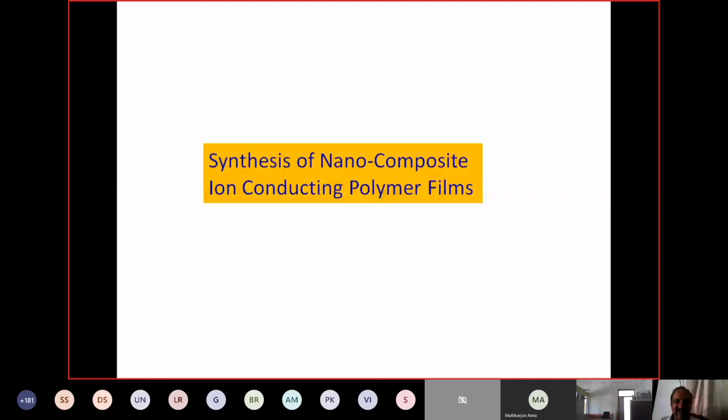So because of that only we are adding these nanomaterials, because nanomaterials have the advantages of high surface area and also a changed quantum confinement effect. In this case, because they have smaller sizes, we can disperse these nanomaterials in these films comfortably. If the size is bulk, it is difficult to disperse, because the films are very thin, even less than 100 micrometers. So that will require smaller and smaller sizes.